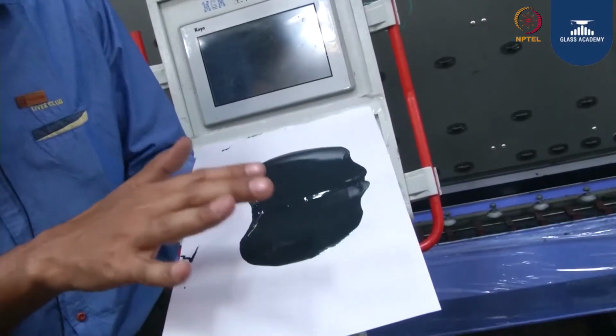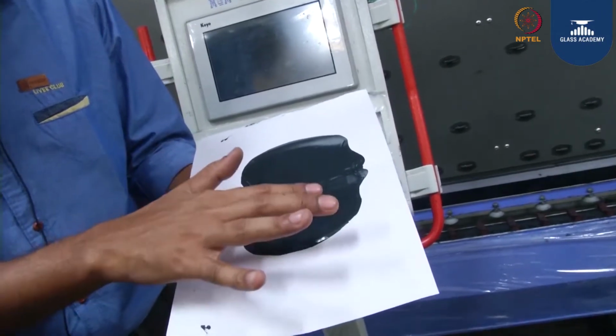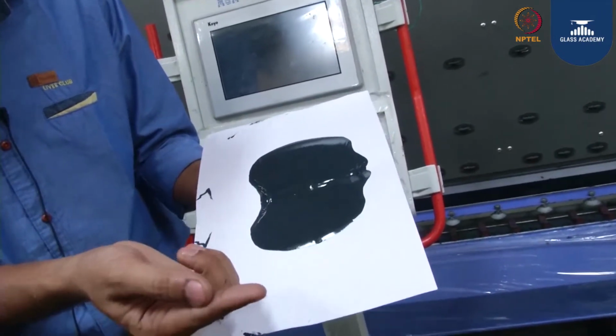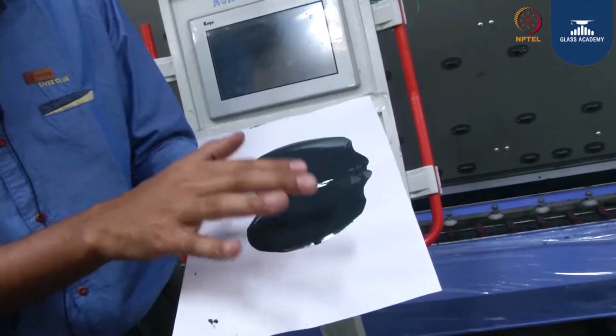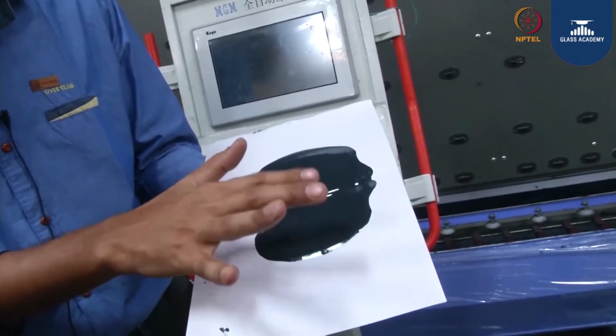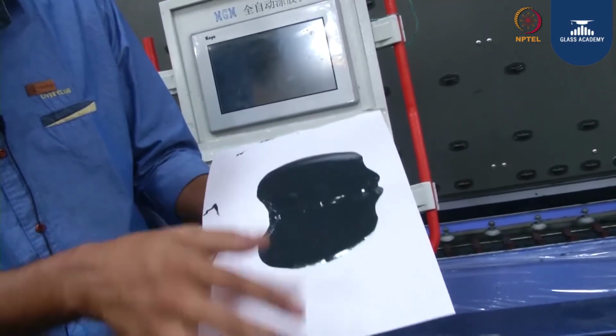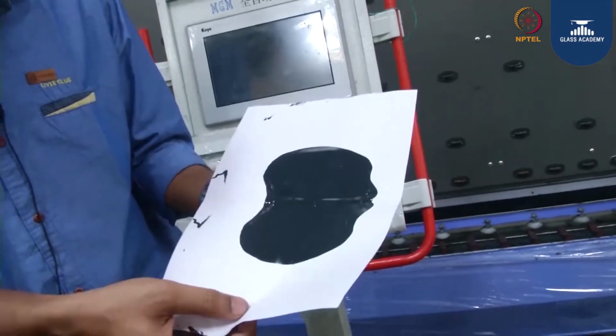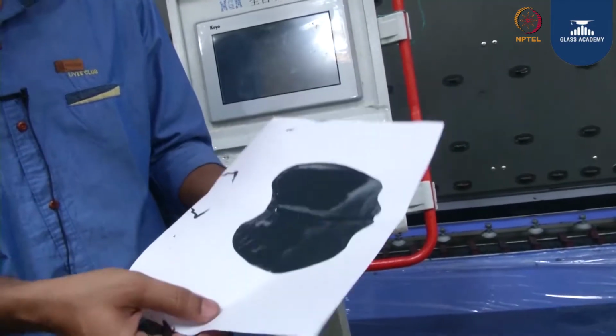We have one more test known as the skin over test. By placing your finger on the silicone, if you are able to feel the wetness after 2 hours, we need to inspect. If it is still touching after 2 hours, it means there is a mixing ratio issue. If it is not touching, the test is pass.